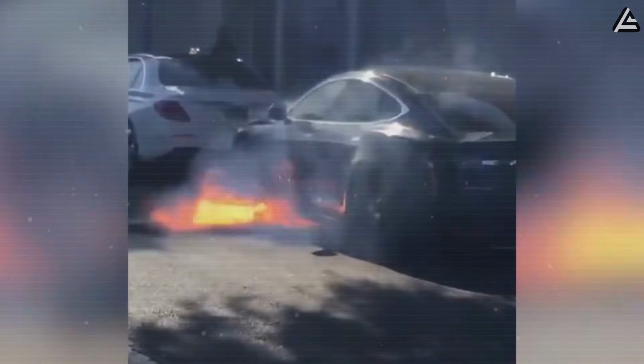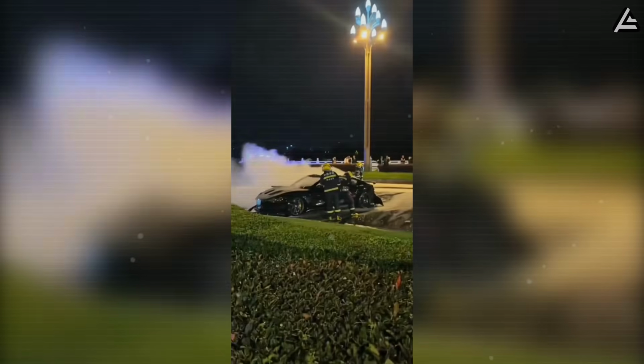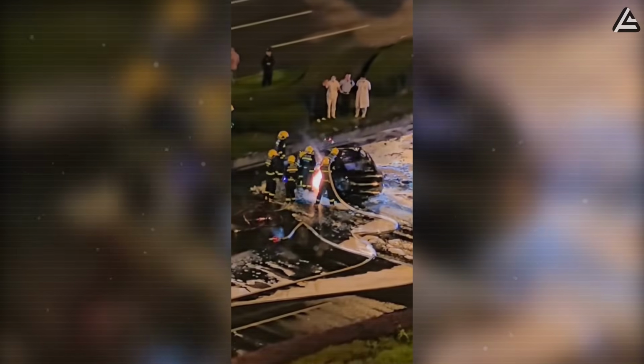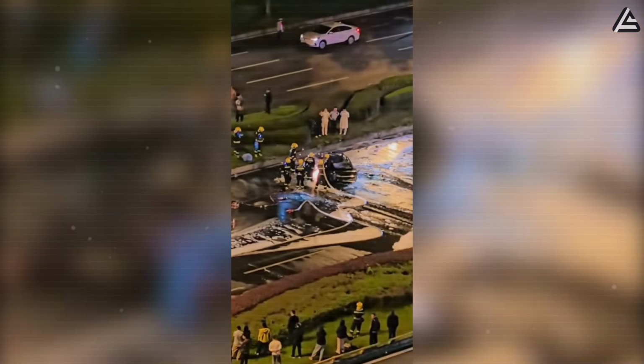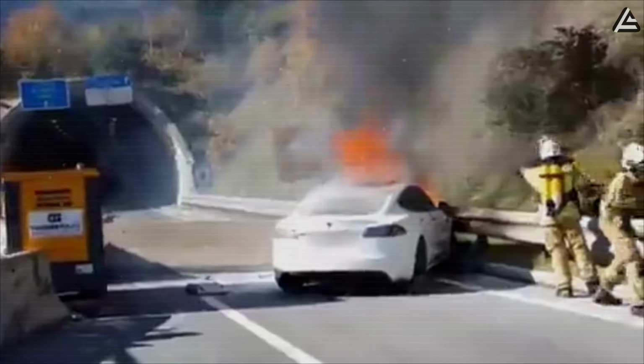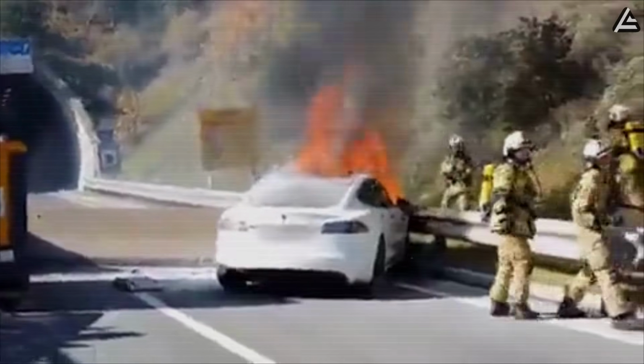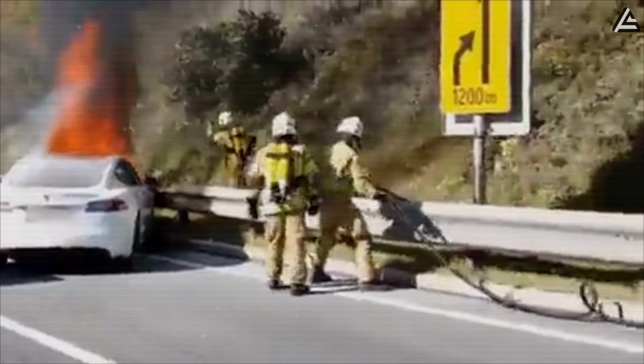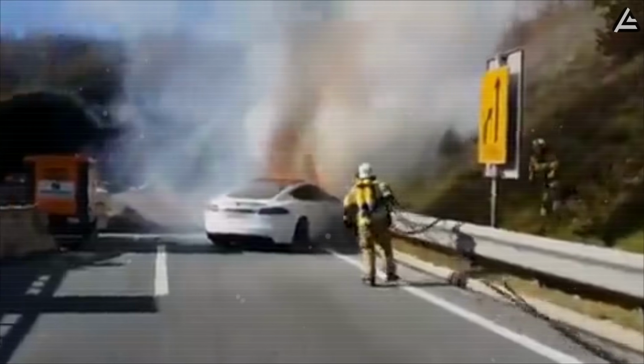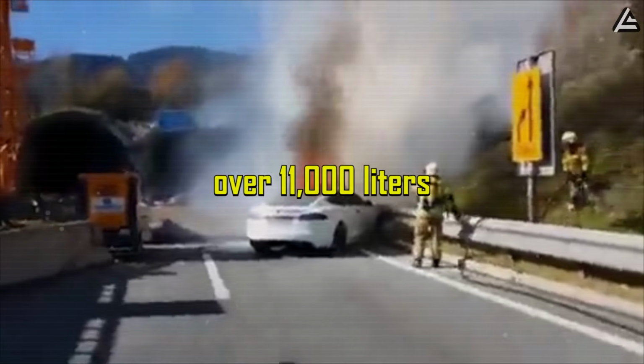When that happens, the heat cascade inside a module can reach 700 to 900 degrees Celsius in under 10 seconds, enough to melt aluminum casing and ignite surrounding materials. Even a tiny puncture or coolant leak can trigger a fire, and once it starts, suppression is difficult. Tests by the U.S. National Fire Protection Association, NFPA, show that extinguishing a large lithium battery pack can take over 11,000 liters of water.